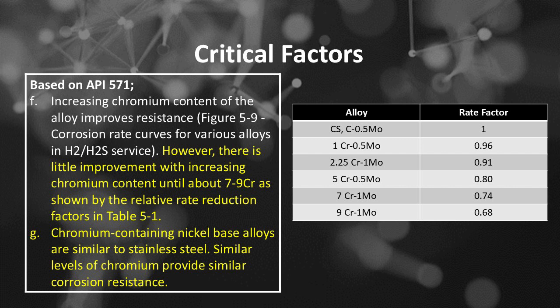This table shows the relative corrosion rate reduction factors for different alloys in hydrogen or H2 and hydrogen sulfide or H₂S environments. The baseline is carbon steel with 0.5% Mo, which has a rate factor of 1. As we increase chromium content, the corrosion rate decreases, but notice the trend. At 1% of chromium, the improvement is minimal, rate factor only drops to 0.96. At 2.25% of chromium, it's still modest, 0.91. Even at 5% of chromium, we're only at 0.80, so the benefit is limited.